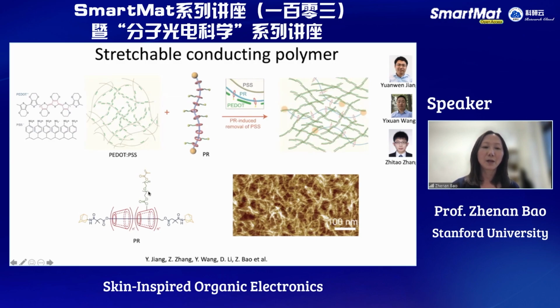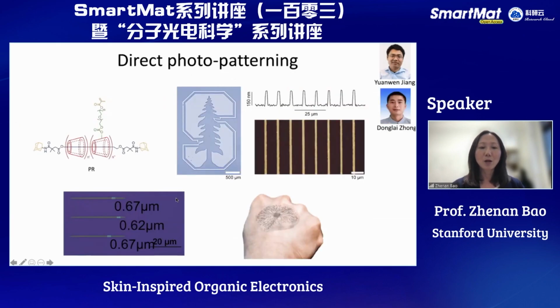But the PEG itself is crystalline, and adding a lot of PEG actually results in a brittle film, even though there's a boost, to a certain extent, to the conductivity. So here, in order to really suppress the crystallization of the PEG, we have to go to the extreme of adding a rotaxane to thread over the PEG. Then the side chains have additional PEGs, which we hope don't crystallize too much, but adding a high density still will lead to crystallization. The other role of the side chain is to carry the crosslinker so that we can pattern the high conductivity PEDOT using this kind of crosslinker. And this can give even submicron feature size, directly photo patterned, but also high conductivity.